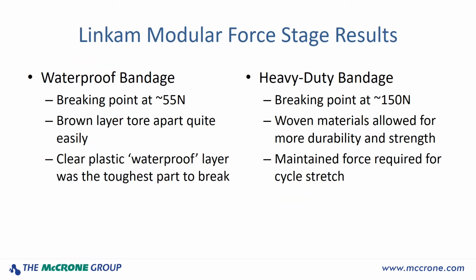All in all, we were able to conduct successful testing on these two bandages and capture some interesting data. For the waterproof bandage, it had a breaking point of roughly 55 Newton, and the brown layer of the bandage seemed to tear apart quite easily even in the smaller cycle stretches. But the plastic waterproof layer of this bandage was very tough to tear in all of the stretches.